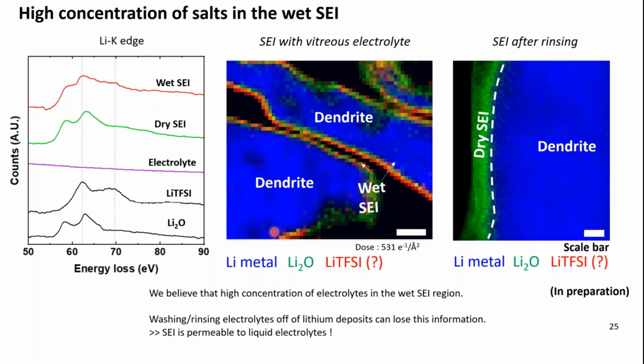And in addition to that, by the fact that the salt information can easily disappear, the SEI is quite permeable to liquid electrolyte and solvents. Unlike our previous idea that SEI is a complete passivation layer, it turns out the SEI is quite permeable to liquid electrolyte and inner solvents. And this observation is consistent with the recent observation of SEI swelling depending on surrounding environments.